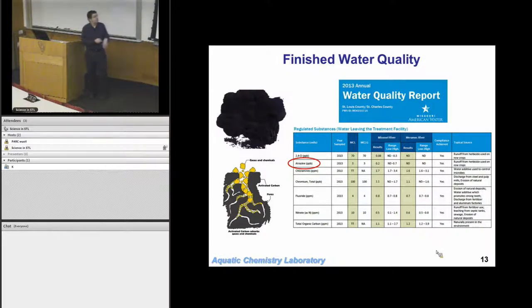Fortunately, by the time we've treated the water, the drinking water standard is 3 micrograms per liter. It's down to 0.2 micrograms per liter. If we didn't treat it, there are certain periods of the year where we would be exceeding the drinking water standard for atrazine. And we do that by using activated carbon. So this is that anthracite, essentially, that you would have ground up to be very fine grains. You actually put in this powdered activated carbon into the water, let it mix, and then it settles out, and it will carry with it some of the atrazine as well as different contaminants.